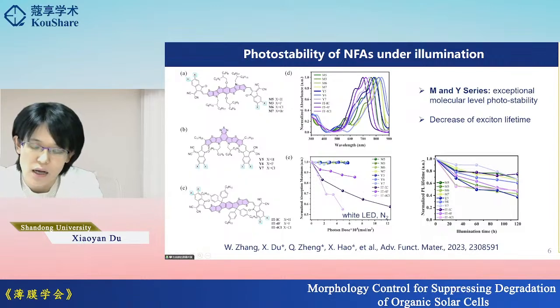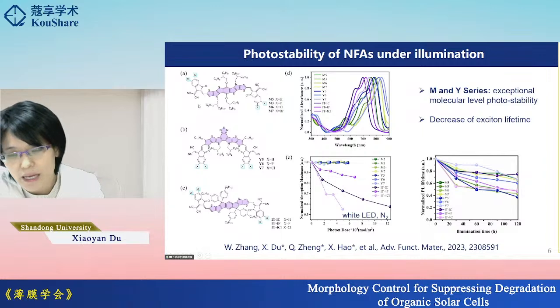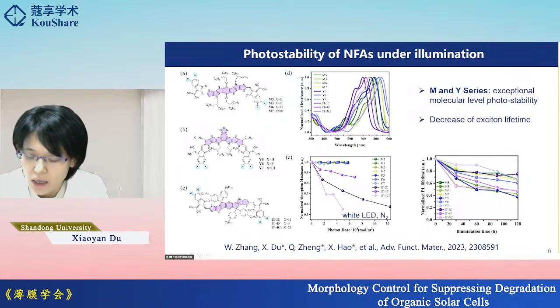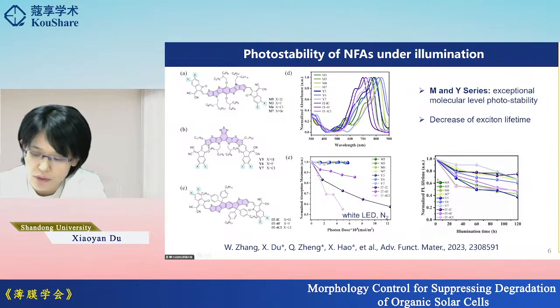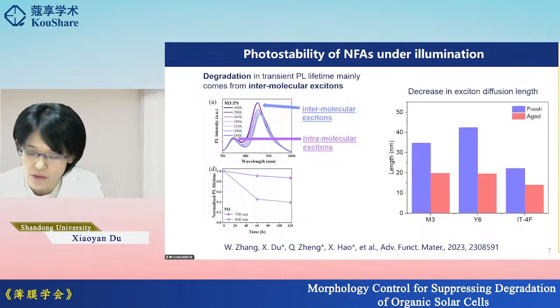However, if we look at the lifetime stability of the excitons, or the PL lifetime evolution under illumination, we see that all these materials show degradation in PL lifetime upon illumination. And this trend is not dependent on the core unit or the end group halogenation. So we don't see any reliable trend depending on the chemical structures. And we know that the exciton lifetime probed here depends not only on the molecule, but also on the interaction or the aggregation states of the molecules in the